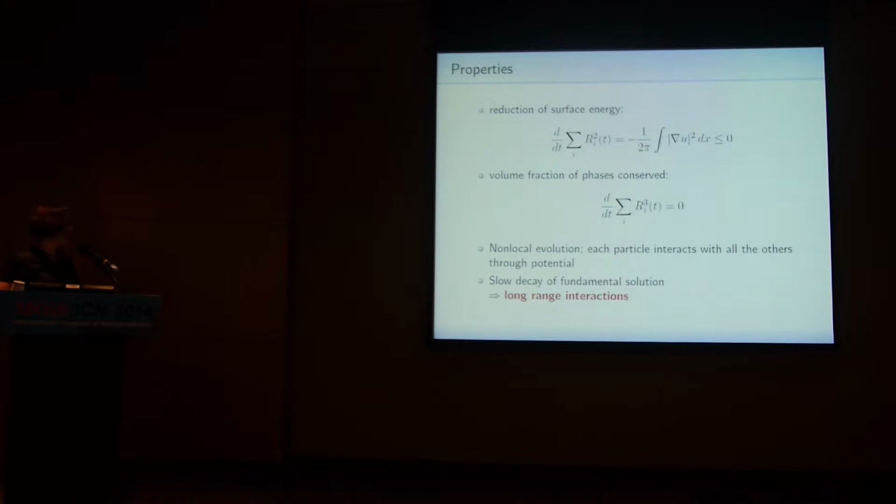And what makes this evolution actually challenging and interesting is that, of course, it's a curvature-driven evolution, but it's non-local because each particle interacts with all the others via the diffusion potential u. And u is governed by the Laplace equation. The fundamental solution in R3 decays like 1 over modulus of x, so it's a slow decay, and we have long-range interaction of the particles. And that's what we need to resolve.